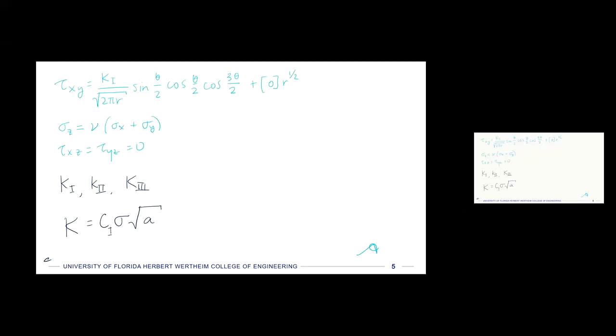And so if we then look at, I'm just going to tell you what these things are. If we go back and look at elasticity theory and how that geometry affects that number, we find that this factor here is equal to square root of pi, right? And so then our new definition for this fracture toughness is stress times the square root of pi times the crack length, so pi a.